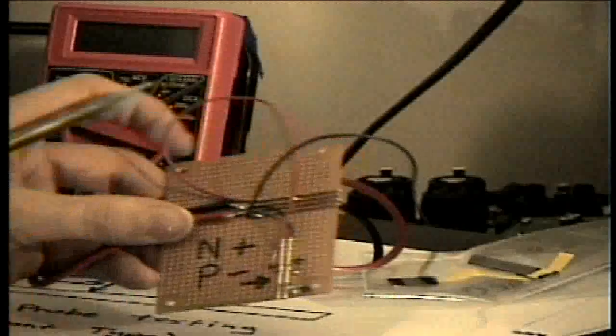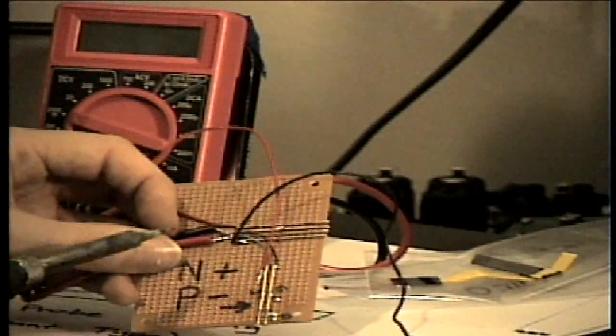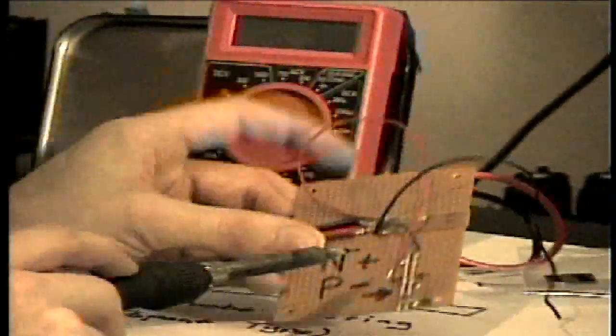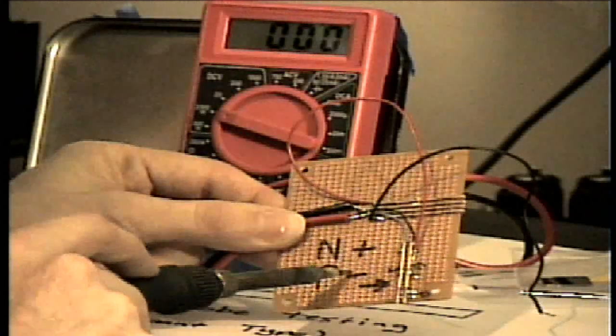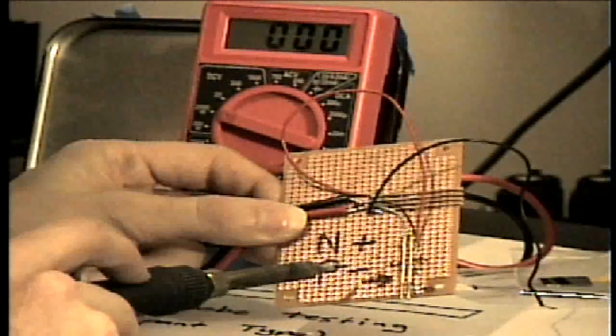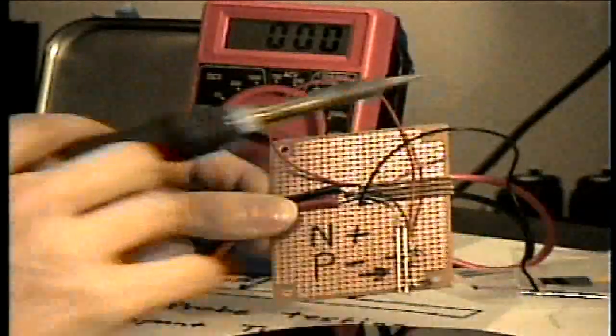When you're testing, if the meter swings to the positive direction, so the sign on the meter shows positive, it's an N-type wafer. That's a phosphorous-doped wafer. If the meter swings to the negative, it's a boron-doped wafer, and that's important when you start doing your semiconductor process.